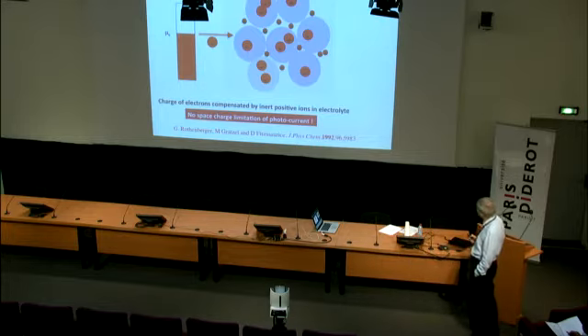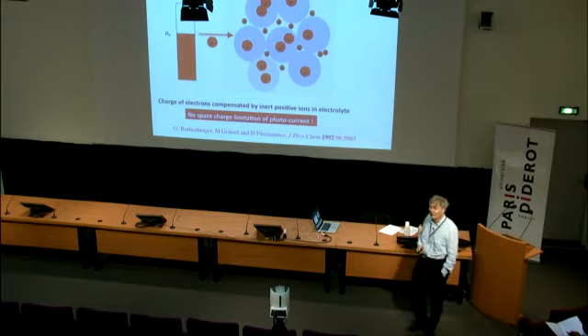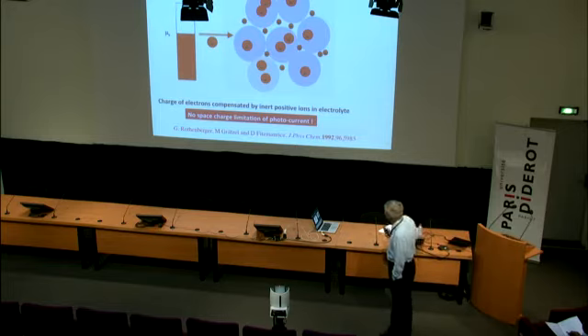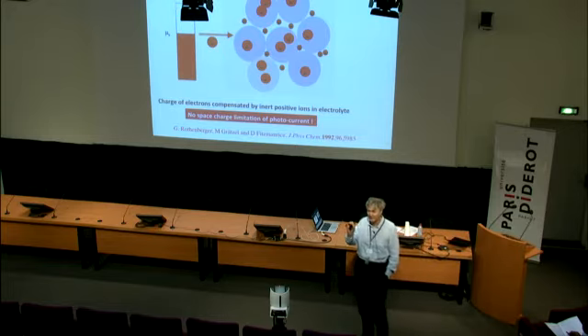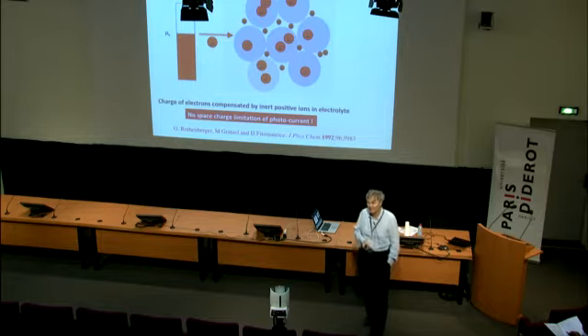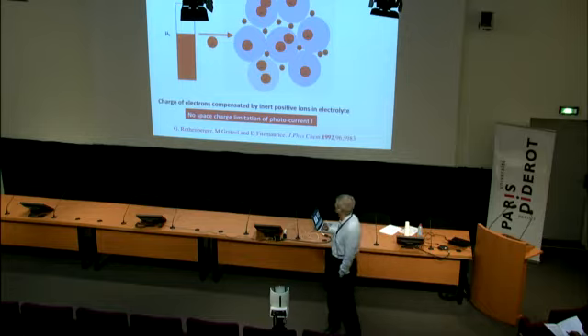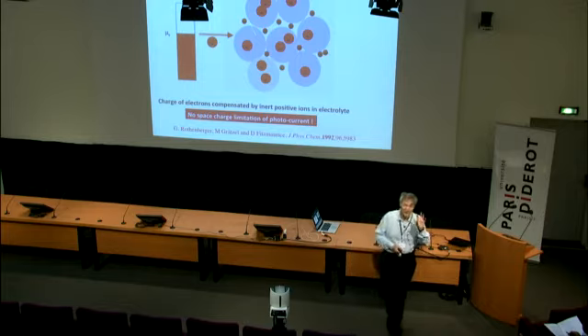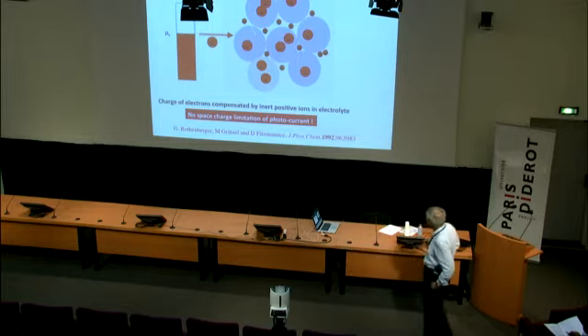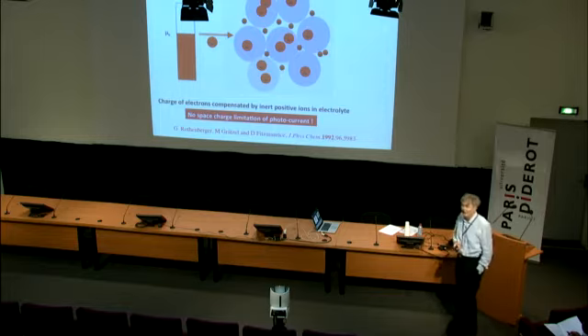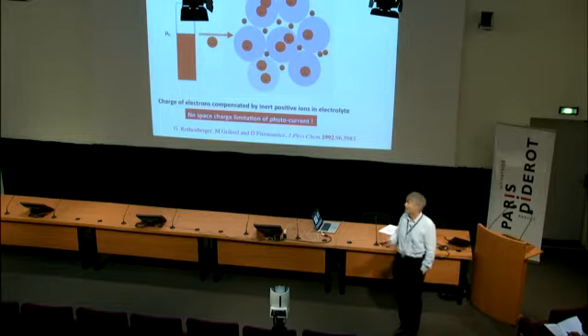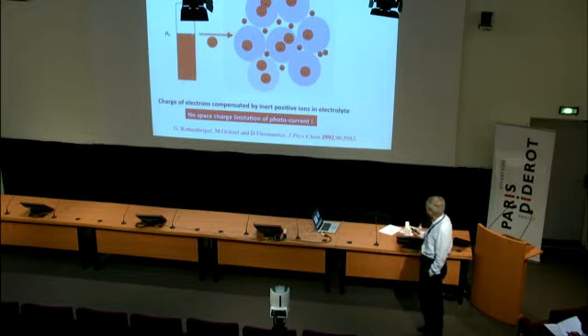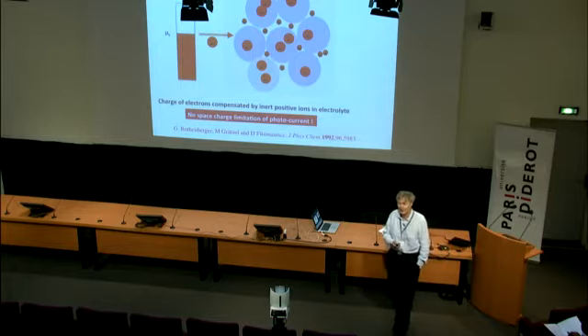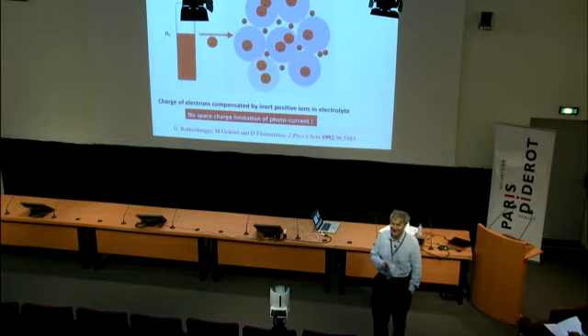But not only that, we also have this nano dimension, which is in the same size range, the size of these particles of the same order of magnitude as the Debye screening length of the electrolyte in the pores. So each particle is screened properly, and that means we can use insulating particles. They're all insulating, they're not doped. And so we can use those insulating particles, inject and withdraw charges, because the charge is screened on each nanoparticle level. That's another critical advantage.